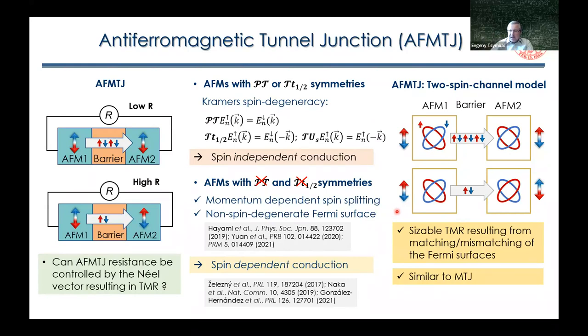But despite this fact, because of conservation, this is an important point I need to mention here. This assumption would work if you have conservation of transverse momentum in the tunneling process, because if you have mixing between different momenta, obviously this idea will not work. So again, I emphasize that this idea is similar to what we have in magnetic tunnel junctions.